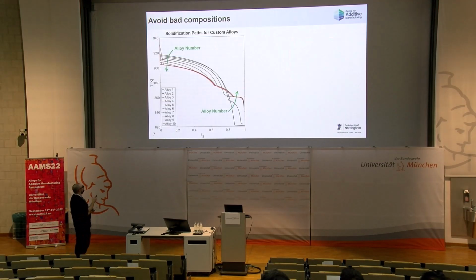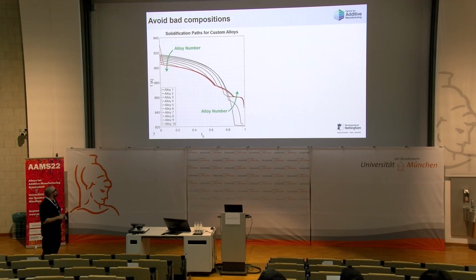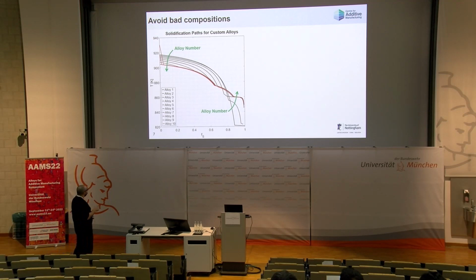Okay, so from alloy 1 to 10, we have a lot of solidification paths, and what we can see is that when we increase the alloy number, so when we put more solutes in our alloy, we have a progressive shift of these curves towards a lower liquidus temperature and a higher solidus temperature. And we start to see with alloy 9 and alloy 10 the first precipitation of aluminium 3 nickel as a primary phase.